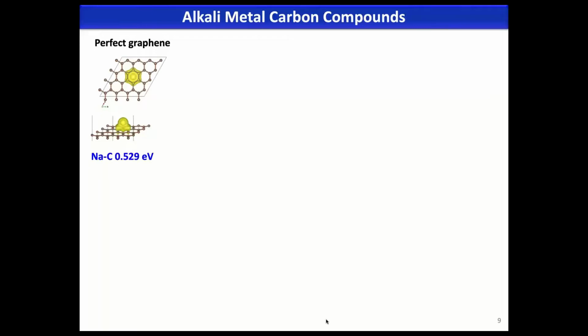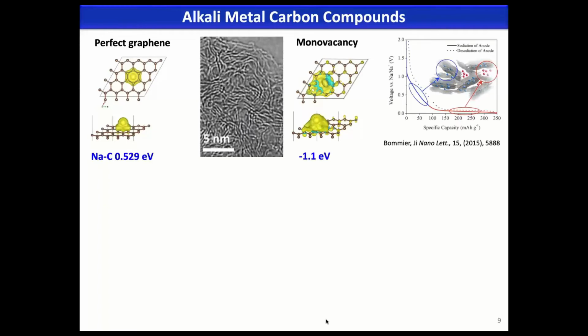It's quite interesting. For example, if you use graphene, you want to store sodium ions in graphite or on the surface of graphene, it's not going to work. Why? Because the binding energy between sodium and carbon is not going to work out. So basically, sodium ions or sodium atoms like themselves better than binding with carbon. But if you actually have defects, for example, monovacancies, divacancies, even curvatures, even a creased or rippled structure of graphene, it's going to help you. It's going to avail some kind of binding with sodium ions.